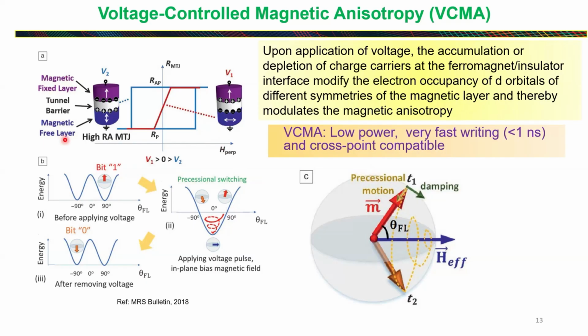For one polarity of the voltage, you increase the PMA, and hence you don't do anything. But for the other polarity of voltage, you decrease the PMA. When you decrease the PMA, if you apply a small in-plane magnetic field, then your spin will start precessing around the in-plane magnetic field. And if you time your voltage pulse very precisely, then you may get both states, up and down. But the problem is that now we are more dependent upon the timing of the voltage pulse, how far you apply the voltage pulse, how long the voltage pulse is. And that has actually created a problem for deterministic switching.